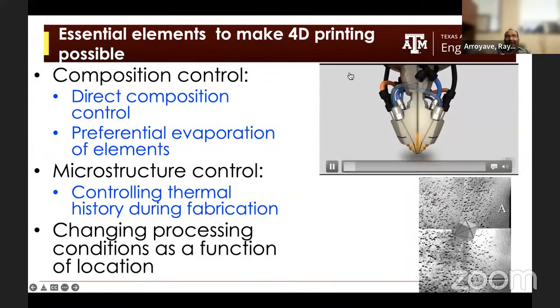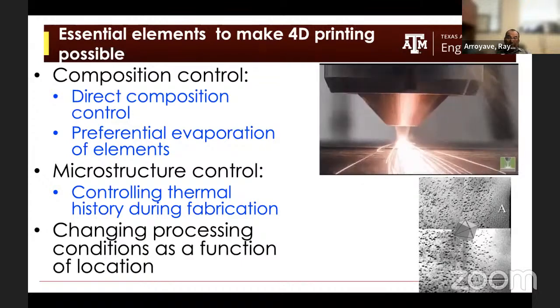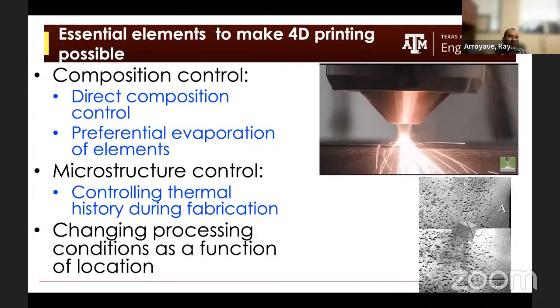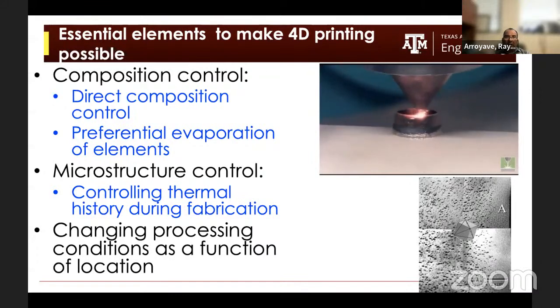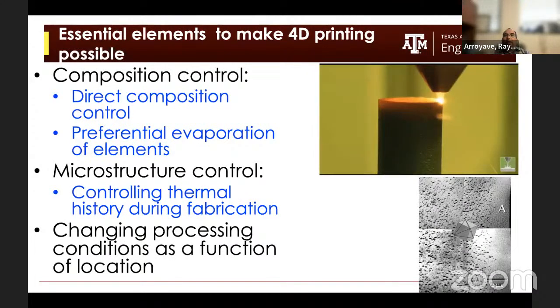So, an essential element to make 4D printing possible in the context of additive manufacturing is composition control. So can we actually directly deposit feedstock that has different chemistries? And there are 3D printing technologies, for example, that allow you to do multi-material printing. I'm going to talk about that in the second half of my talk. Or, in the case of a material like a shape memory alloy that is extremely sensitive to chemistry changes, could we actually exploit the fact that different elements in the alloy have very different vapor pressures to then enable the preferential evaporation of elements in such a way that we could locally control the chemistry?